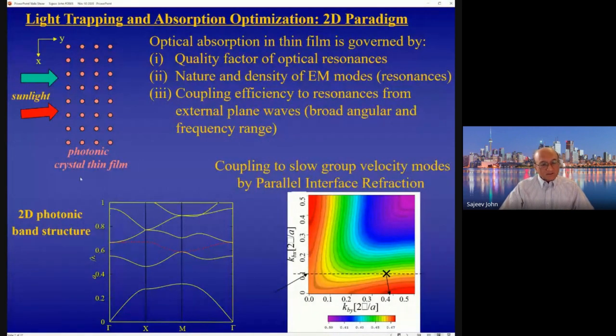So if you have a periodic structure like this, one thing that can happen is that light can bounce back and forth inside the structure many times before it reflects or is transmitted. This is what we refer to as slow light. Here I depict a band structure diagram of a two-dimensional periodic structure. This is wave vector along the horizontal axis and a over lambda, or frequency, in the vertical direction. You see, for instance, at this frequency, there's a band, this red dashed line, which is very flat. That means that the group velocity of light is very slow. That means that light is bouncing back and forth inside the structure as it's propagating through.